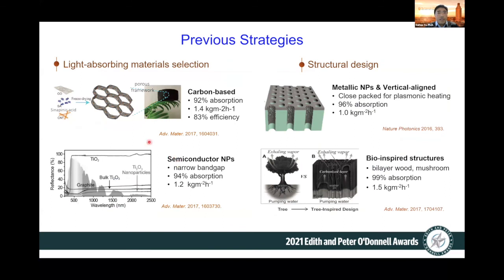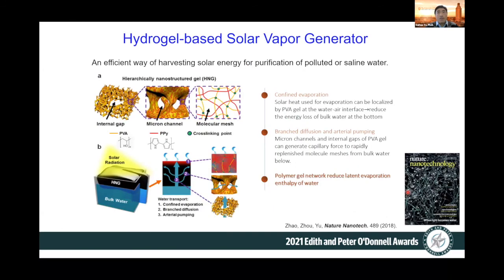Previously, in the solar vapor generation field, two general methods were explored. Typically, it's using different types of light absorbing materials, which can be carbon-based or semiconductor nanoparticles, or changing the structural design, involving self-assembled monolayer particles with the nanoplasmonic effect to enhance solar light absorption, or bio-inspired structures that use the 3D architecture of wood to improve the solar evaporation rate. But generally, they are limited to a rate of about 1.5 kilograms of water per square meter of active material per hour of operation. So recently, we discovered that hydrogel is a very promising class of material for solar vapor generation.